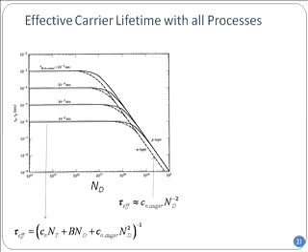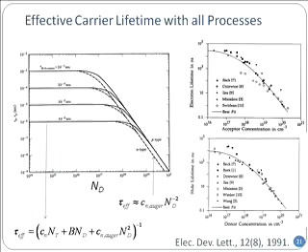Now remember, this is a log-log plot. So if you take a log-log on the tau effective on the left and right-hand side, what should be the slope of that line? -2, right? If you look at this curve, you will see exactly -2 is the value on this curve. The slope on the high side is exactly that value. And experimentally, people have seen very similar results. That's the theory. So you put various values of ND and you can generate the curve.